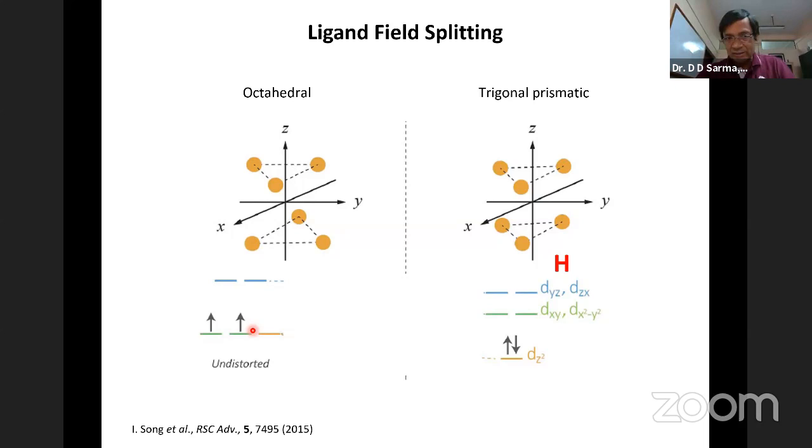The twist is that you can see that it's a degenerate state, which means it will tend to have a spontaneous Jahn-Teller distortion. These will not remain symmetric triangles as shown over here, because energy can be lowered by making small distortions. And such small distortions, if they happen, and theoretically it's predicted they'll happen, in this particular state will lift this degeneracy that makes it metallic, making one level go down and two levels go up,